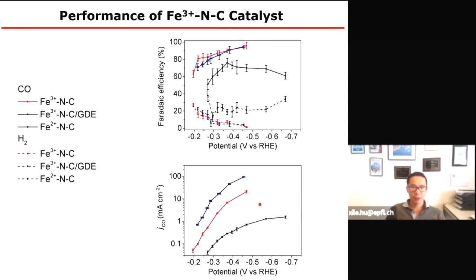We checked the CO2 performance, using our iron 3 NC compound. We made the iron 2 NC compound from the literature as a reference. We used both a 3-electrode setting and a gas diffusion electrode setting. This is the iron 3 NC compound. We were quickly happy to see that these catalysts are really selective for CO2 reduction to CO, with more than 80% Faraday efficiency easily. The other side product is basically hydrogen.